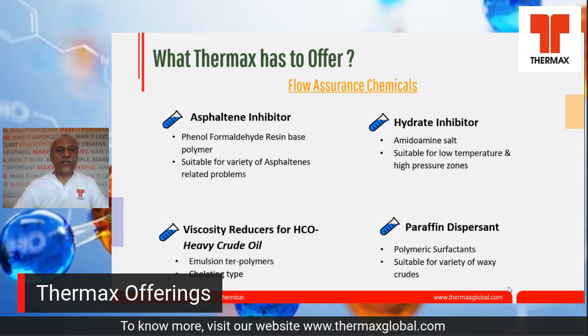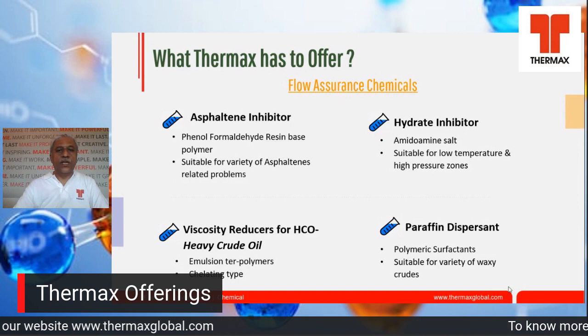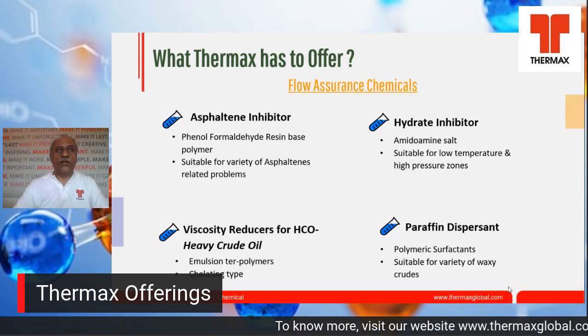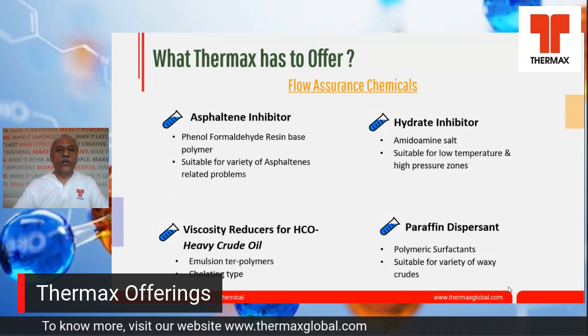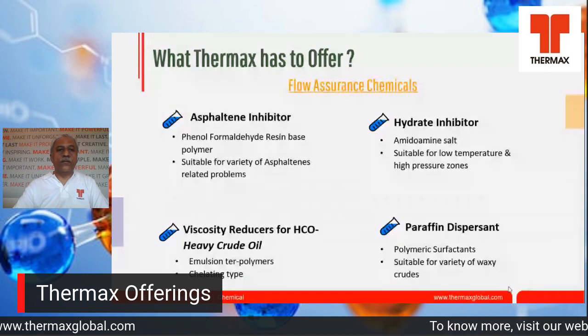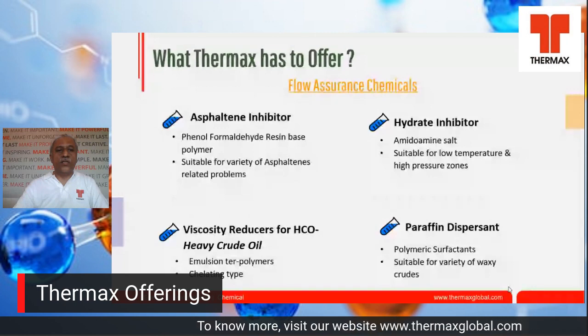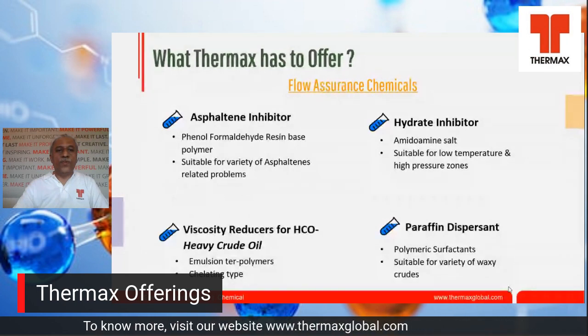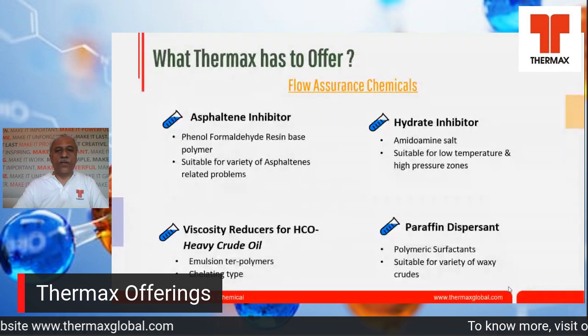Then we have various viscosity reducers for heavy crude oil. As we discussed earlier, for heavy crude oil or super heavy crude oil which have pour point of 45 and above, pour point depression or pour point improvers doesn't work. So in that case, we normally use viscosity reducers. So we have one type of emulsion polymer which can act as a viscosity reducer.